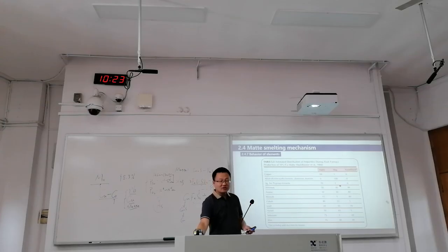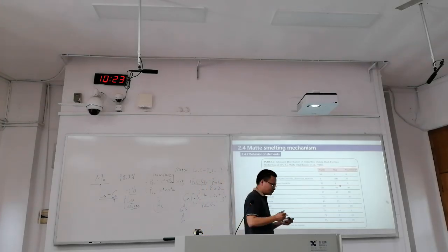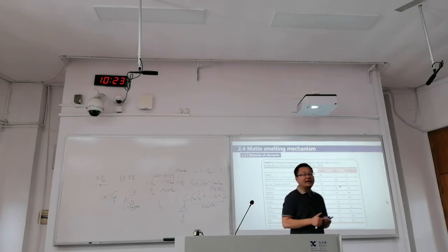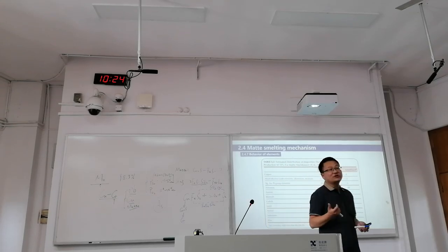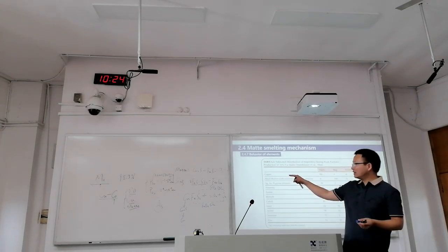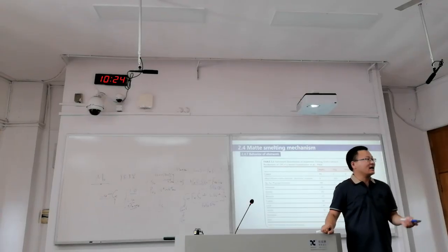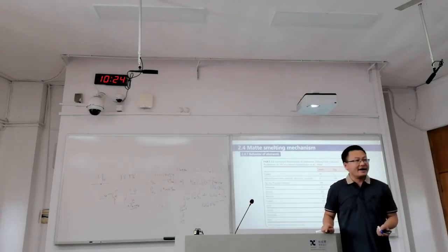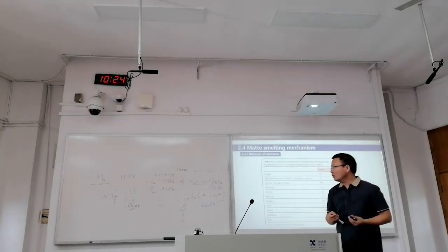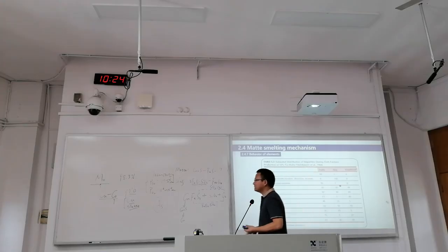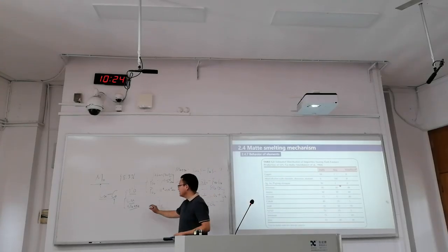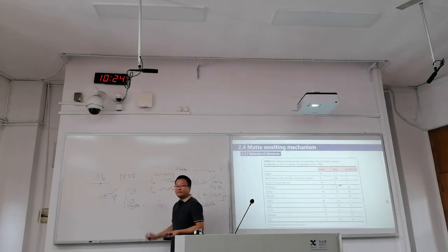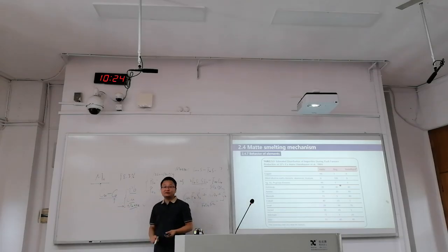When we are recycling our cell phones, when we are recycling the copper mines, we need a big or good recovery of PGMs. And you can use lead as collector, copper as collector, matte as collector, and the solid solution. Our conclusion is that when we are processing those PGMs in a matte containing system, matte is the best collector.